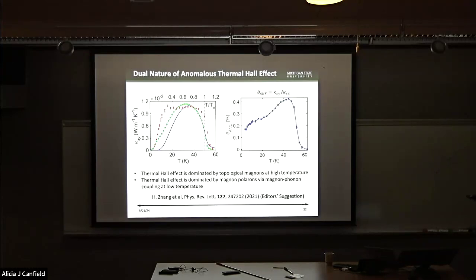The green curve is the calculated thermal Hall conductivity taking into account the magnon phonon scattering. And immediately we can see that at low temperature, indeed it captured some of the thermal Hall conductivity that we observed experimentally. And the figure on the right just shows the temperature dependence of the anomalous thermal Hall angle, which is defined as the ratio of thermal Hall conductivity to longitudinal thermal conductivity. And basically, we can divide this figure into two regions. For the high temperature region, the thermal Hall signal is dominated by the topological magnons. And at low temperature, the thermal Hall signal is dominated by the magnon phonon hybridization.